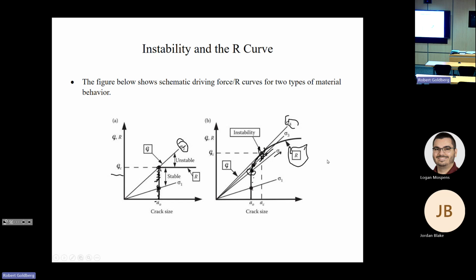You don't get distinct curves. And the point here is that this relates to the idea that the value at the initiation of crack growth is what determines this a sub 0. In our theory, we can say our initial crack size is obviously this. But what this whole discussion related to is that when you do a real experiment, determining that precise point where you get a crack in the structure is not so easy.